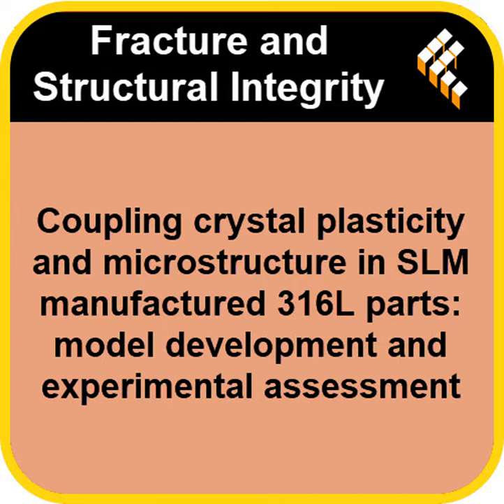But what about the elephant in the room for any SLM part? Residual stress. All that rapid cooling must lock in massive internal forces. It does, and they had to account for that. They modeled the stress based on the vertical printing process. They assumed a maximum residual stress of 190 megapascals. The radial stresses were equal, about 95 MPa, and the stress in the build direction was basically zero.